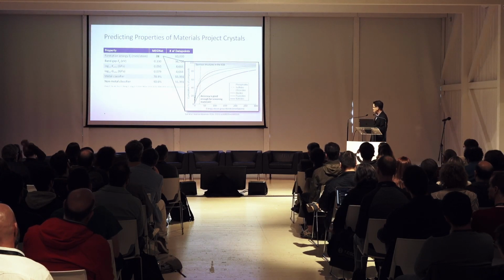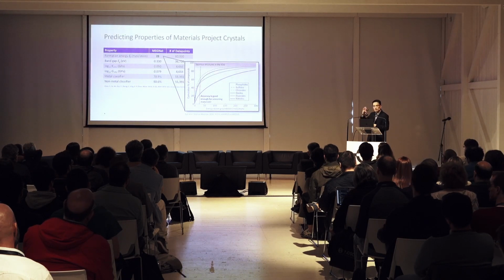With an accuracy of about 28 milli-electron-volt per atom, we are at about one-third of the error, one-third of about 100 milli-electron-volt per atom. In other words, with this accuracy, we can already estimate pretty well whether a material is likely to be synthesizable or not. So this is quite a reasonable accuracy for this purpose, right?